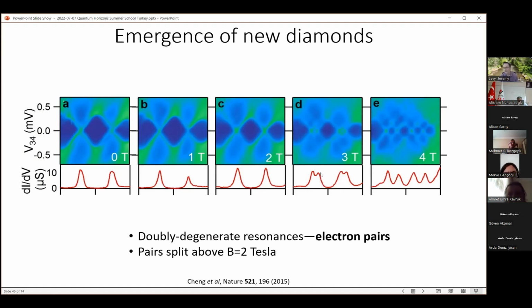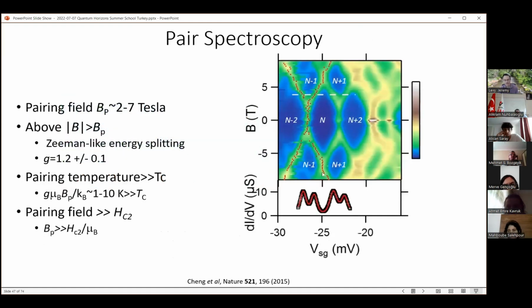And so it took us some time to understand what this was, but really we had to reinterpret these diagrams because we believe now that these are stable states of pairs of electrons, not single electrons. And they break apart, in this case, at 2 Tesla. So another way to see this is to make an intensity plot of the zero bias conductance as a function of magnetic field along the vertical axis and the gate voltage along the horizontal axis. And the dark regions are the blockaded regions, and the bright green yellow regions are the places where you have conduction. And the assignments are that this is a state in which there are n-2 electrons in the island, and then it jumps into n, and then n+2.